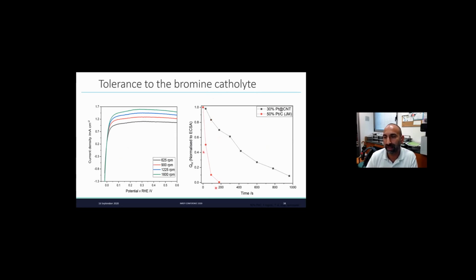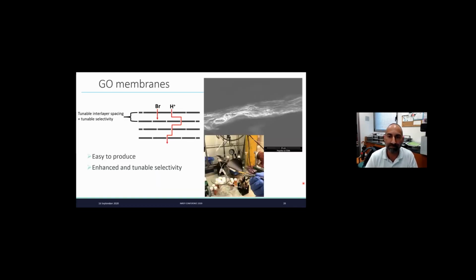So this is the platinum on carbon from Johnson Matthey that we use as a reference. And this is the platinum on the nanotubes. And this is very stable with this aggressive test. That's the best result that we had until today, better than the polydopamine and the Titania.